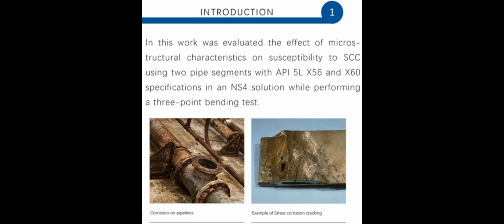Well, in the petroleum industry, the transportation of hydrocarbon is done using low carbon pipeline grade steels due to economic and safety reasons. However, pipelines are always exposed to different types of damage, with stress corrosion cracking being one of them. Stress corrosion cracking is a phenomenon that is commonly observed in high pH environments. However, studies have shown that it can also occur in environments with near neutral pH.